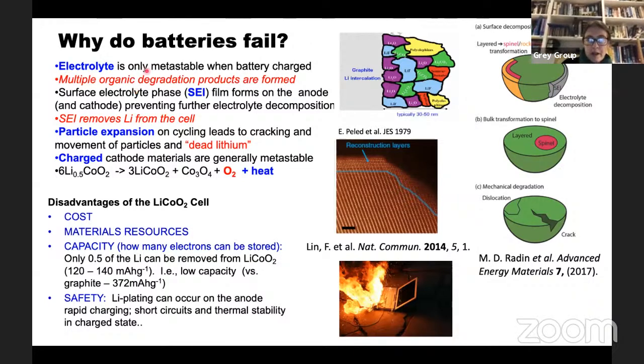And so the only way that batteries survive is you form a passivating layer on the surface of the graphite. It's called the solid electrolyte interphase, or SEI. And this forms a passivating layer in the same way that you have rust on iron, or the copper metal is typically bluey green, not because copper is that color, but because the passivating layer is, and that prevents further reaction. So the same thing is going on in the battery.